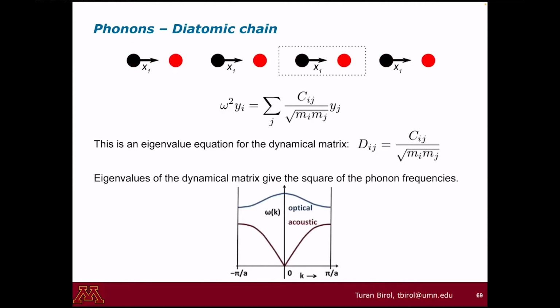Sorry to interrupt. What are these masses? What did you actually put there in the code, or when you do phonons? Oh, it's the atomic mass. So the atomic mass, I see. Yeah, and the units can be somewhat of a headache every now and then because masses are reported in grams per mole, whereas you have the force constants usually in something like electron volts per angstrom square. So keeping track of the masses is sometimes tricky, but it's just the mass of the atom.